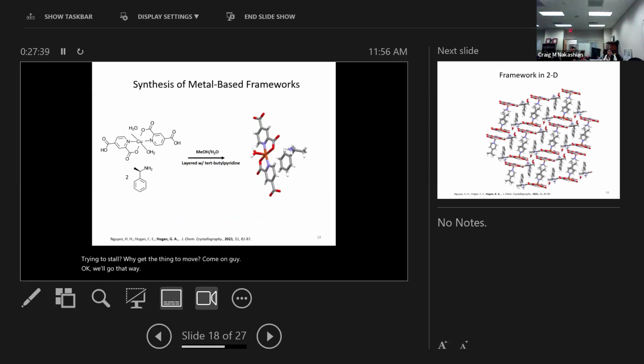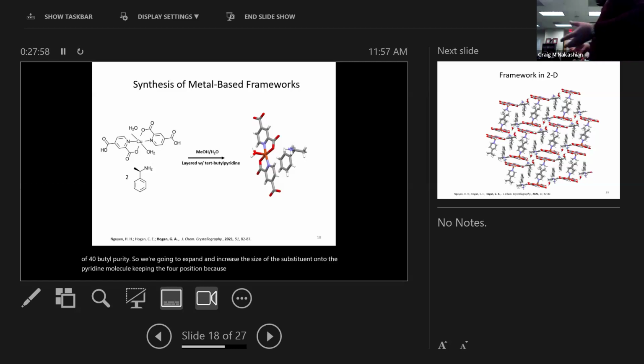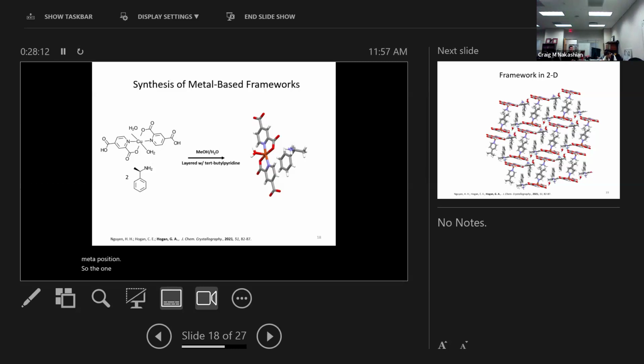So one of the last ones that we'll have. Same framework. Now we're going to look into the use of 4-T-butylpyridine. So we're going to expand and increase the size of the substituent onto the pyridine molecule, keeping the 4 position, because what we have noticed with almost all of our included frameworks is that anything on an aromatic molecule, if it's on the ortho or meta position, so the 2 or the 3 position, we're not seeing complete guest inclusion. The longer, straighter, the better. Okay, so that's why we look at 4-T-butylpyridine, to expand the size of our guest molecule inside the framework, to see, do we have enough space?